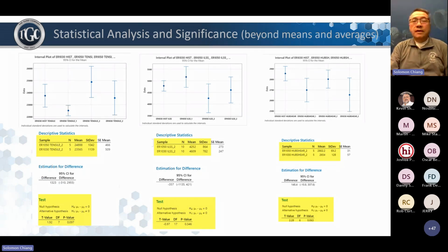So, for example, in a material substitution situation, not only do we compare the properties of the candidate to the historical result of the incumbent, we also test the incumbent and the candidate side by side. We use the same aging, the same conditioning method, and the same test method. And then once we have all those results, we can apply statistics and ANOVA testing to see if we are indeed seeing a difference or it's just natural variation.